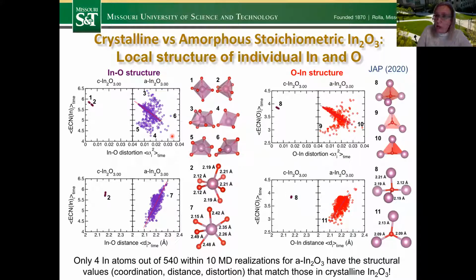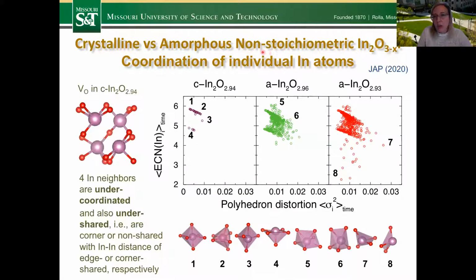So this was stoichiometric, with exactly the perfect stoichiometry of the material. As we change to non-stoichiometric, reducing the oxygen content, we begin seeing many more outliers and much lower coordination configurations. For example, the coordination becomes 3, or maybe even 2 in some cases. And so we start developing localized states as we go to more and more non-stoichiometric cases. But again, we would like to compare to the oxygen vacancy that has been studied a lot in these oxides, and try to develop essentially the descriptors for the structure. What should we look at exactly in order to be able to predict the formation energy of these defects?